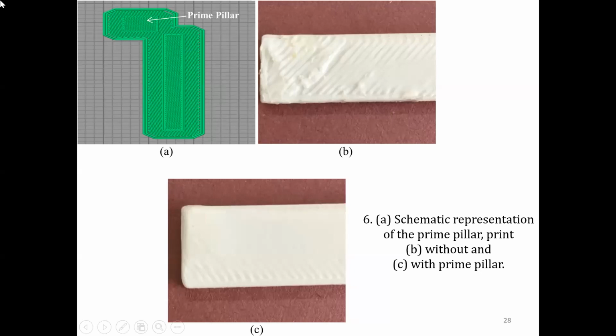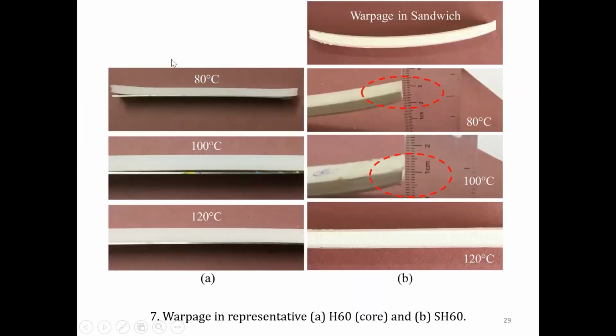So here, the prime pillar is nothing but some additional material which we print before printing an actual sample. Though this is not going to be of any use, it is to make sure that the material flows out well for the actual sample. So you can always utilize this prime pillar when going for a multi-material system to have a good flow. Now let us talk about a very crucial element, that is warpage. And this happens quite often when you are going for a multi-material system.